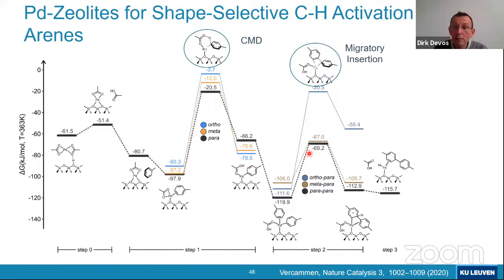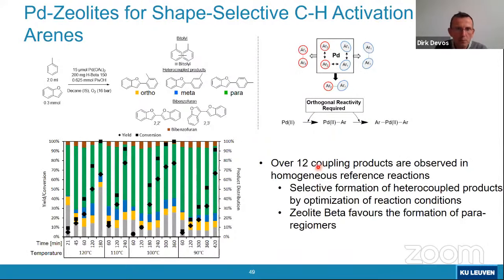In the second step, where we have this migratory insertion, we are less sure why there is still quite a high selectivity, but overall the result remains, of course, that we have a very selective formation of 1 out of the 6 potential isomers of, for instance, bitolyl.